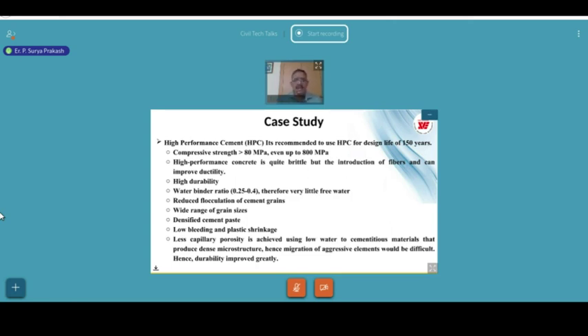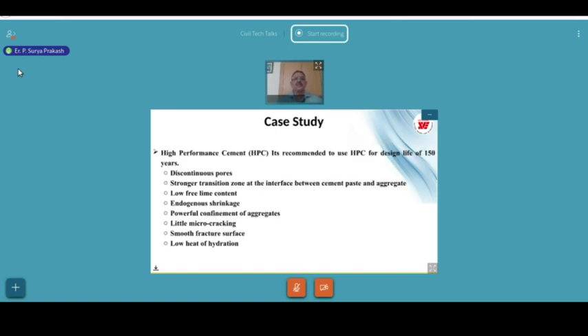And water binder ratio, again the same, and reduced flocculation of cement grains, wide range of grain sizes, densified cement paste, low bleeding and plastic shrinkage. Less capillary porosity is achieved using low water to cementitious material that produces dense microstructure. Hence, migration of aggressive elements would be difficult. And high performance concrete has discontinuous pores. This is very important. This is the design mix criteria, and stronger transition zones at the interface between cement paste and aggregate, and low free lime content, and endogenous shrinkage, and powerful confinement of aggregates, little micro cracking, and smooth fracture surfaces, and low heat of hydration. These are all the parameters.